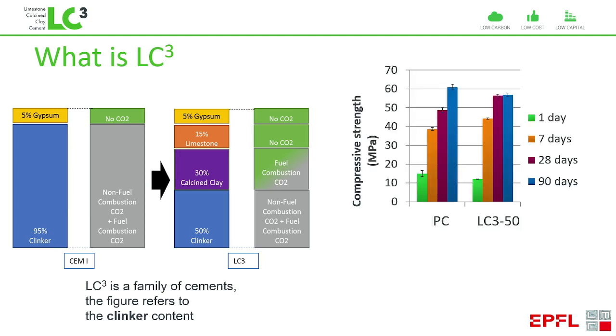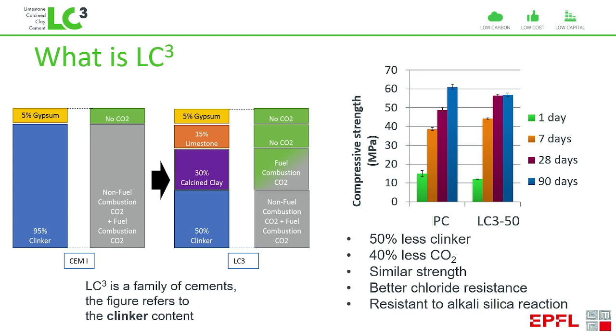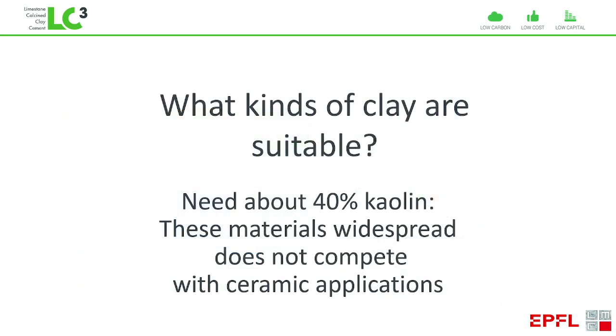And what's really interesting is the fact that with this material, we can obtain the same or higher strength than the reference Portland cement in as little as 7 days. So in a nutshell, we have 50% less clinker, 40% less CO2, and some properties like resistance to chloride ingress and alkali silica are immensely improved.